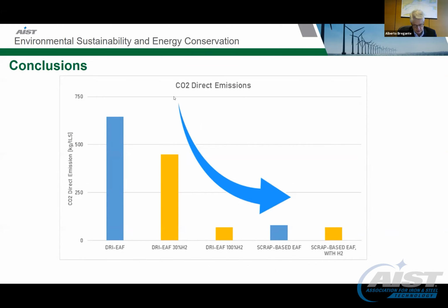So the last slide is recalling the first slide where we took away the blast furnace and basic oxygen furnace, and we started as a reference the actual DRI with EAF fed by natural gas. And with the solution that we presented, we believe that we can help our customer to go towards a dramatic reduction of the CO2 direct emission, both in the route integrated from DRI and the route from scrap-based EAF. Thinking in this way, more economically, that could be the future, also to have access to several customers in the world. Thank you very much.